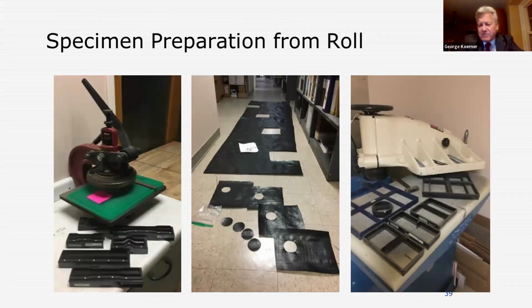Preparing test specimens from the roll good is extremely important. You should get a statistical average across the material. Many test methods are silent in this regard, and in that case, you should use the general practice outlined by either ASTM or ISO.